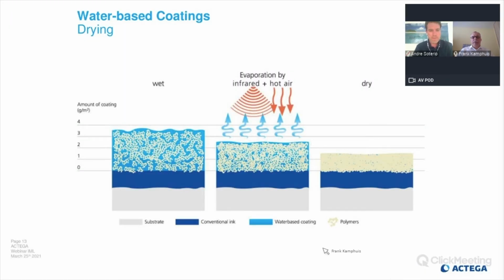If you apply a water-based coating, then you have to think that there's a solvent inside, that is the water, and you have to evaporate the water with infrared and hot air, and then these polymers melt to a solid film. So if you apply 4 grams liquid water-based coating, you get 1.5 to 2.0 grams per square meter solid film.